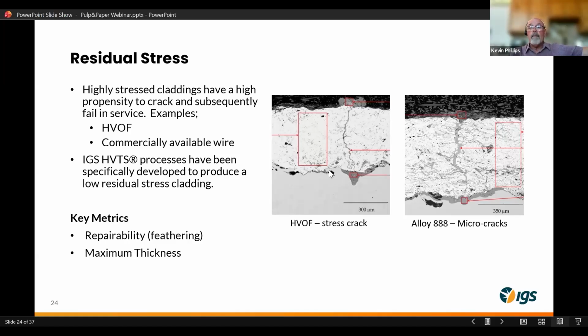which will result in stress cracking in the cladding, and again, creating that pathway for the constituent to attack not only the substrate, but to also greatly affect the effectiveness and the lifespan of the cladding itself. And then commercial wires, such as what's utilized by just TSA or low velocity thermal spray applicators. Again, a lot of micro cracks in the as applied cladding.